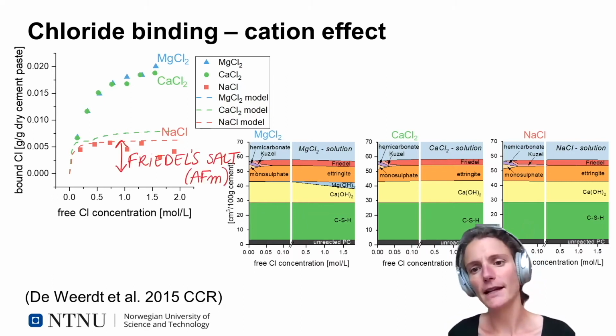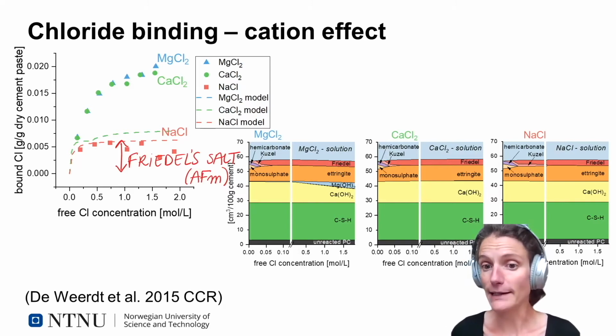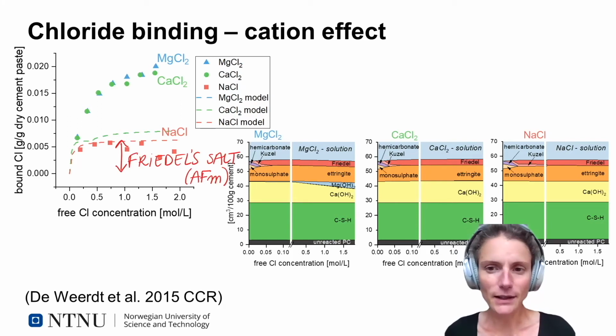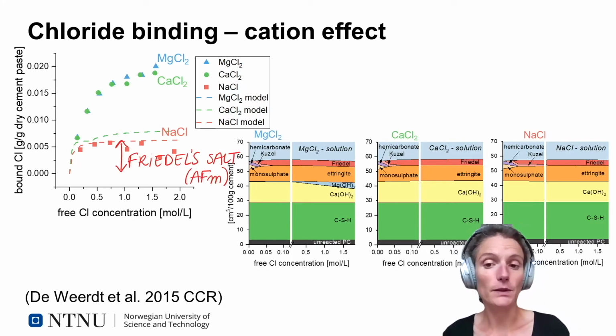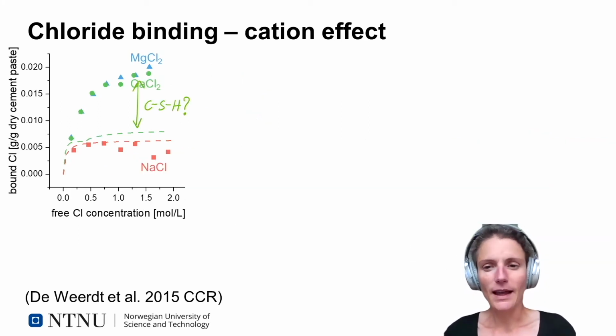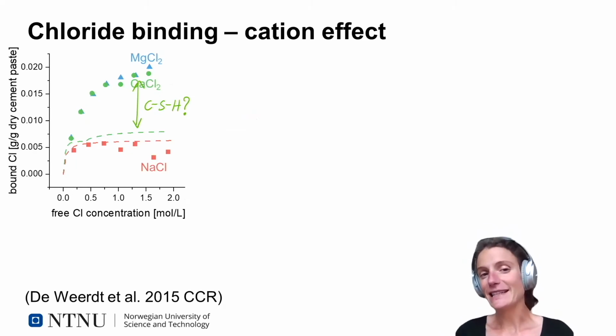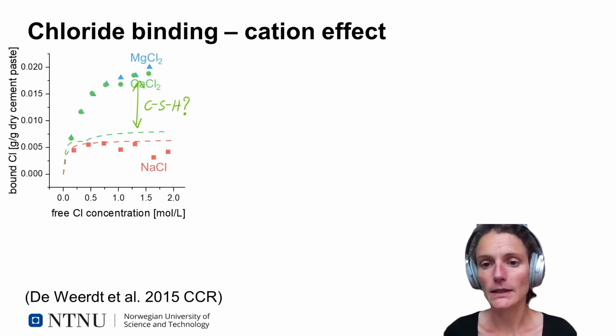And the reason for this is that the thermodynamic model actually predicts chloride binding in chloride AFm or Friedel's salt. So it doesn't account for any chloride adsorption in the C-S-H. And that for us gives an indication that this difference might be due to C-S-H.